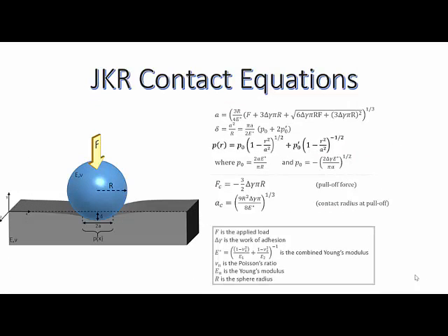You'll notice that in the pressure equation, we have the same term we found in the Hertzian formulation. The other term was neglected because we assumed that no tension or negative pressure could be sustained at the interface. But when we add in adhesive forces, we see that this term is in fact valid. You'll notice that this term is dependent on the surface energy, since it is these interactions that create the adhesion.